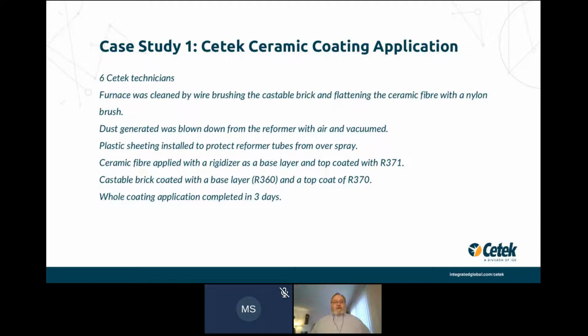So we sent 6 technicians. They worked one shift per day, one 12-hour shift per day. They cleaned the refractory by wire brushing the castable or brick inside the unit. And we cleaned the ceramic fiber with a nylon brush. You'll see flattening there, the ceramic fiber.